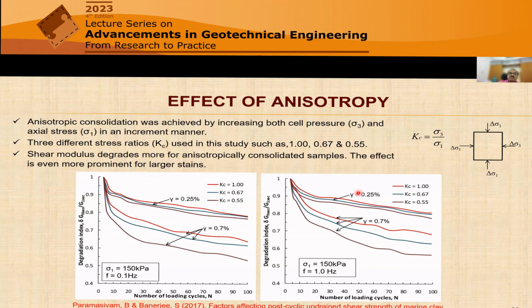Now with that, we try to do the degradation. We did a detailed study, but I have shown you here the degradation part of it. We saw that, you see, this red line is for the isotropic, the blue line is for Kc of 0.67, and finally the brown line is 0.55. And you can see the degradation is very, very significant if you are talking about that higher stress-induced anisotropy. And it's even more interesting if the frequency is less, and with a higher strain, it is very significant as well.